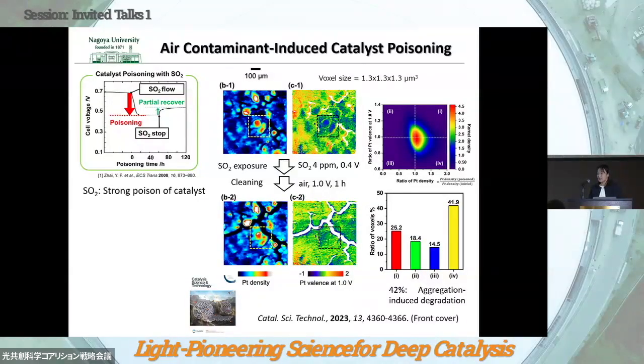And sulfur, this is another important topic for catalysis. Sulfur is well known as a strong catalyst poison. For fuel cell vehicles operating in air, catalyst poisoning by sulfur compounds as an air contaminant is critical. When a small amount of SO2 is introduced to the cathode, the power output of the fuel cell drops immediately. Sulfur is strongly adsorbed on the catalyst surface, although it can be removed by applying a high potential to oxidize and wash it off. Such treatment inevitably degrades the other components. As a result, sulfur is considered one of the most serious poisons for the catalyst.